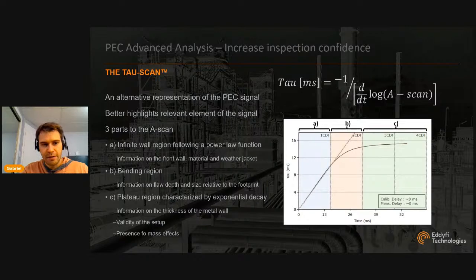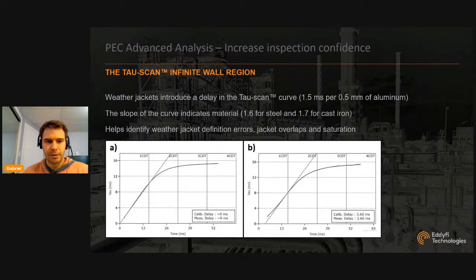There are three parts to the Tau scan or to the A scan. So there's first, in blue, an infinite wall region. You see that the slope is constant within that region. That provides information on the material that you're inspecting, if it's cast iron or carbon steel, as well as the weather jacket. Then there's the bending region, the second region of the Tau scan, that provides information on flaw depth, as well as the size of the flaw relative to the probe's averaging area or footprint. And then there's a plateau region that's characterized by an exponential decay. So that's the nearly constant slope that you'll see in our A-scan representation. That provides information on the thickness of the material, the validity of the setup, the presence of mass effects, noise, things like that.